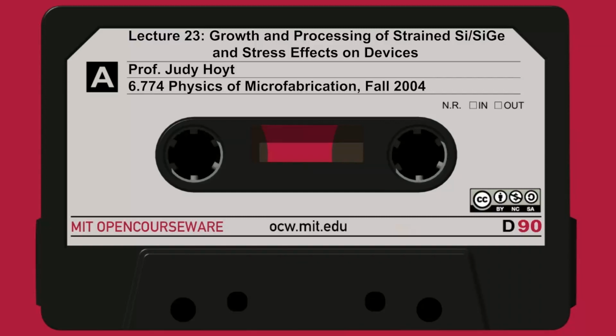So these are smooth undulations. They don't really mess with the electron mobility. The electrons and holes don't care about them. It makes the wafers look ugly, however, and it makes lithography a little difficult because the optical machines don't like looking at plaid. They like things that look smooth. So it is a practical problem. People have found ways around it. You can CMP the layer and remove all the undulations, and it's not necessarily a big problem, but it is an issue.